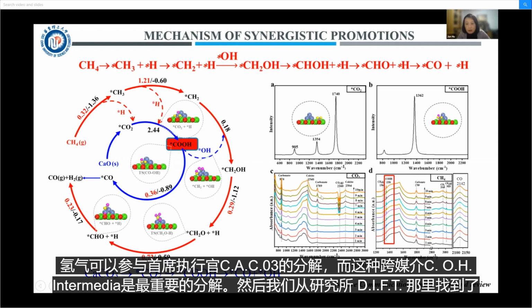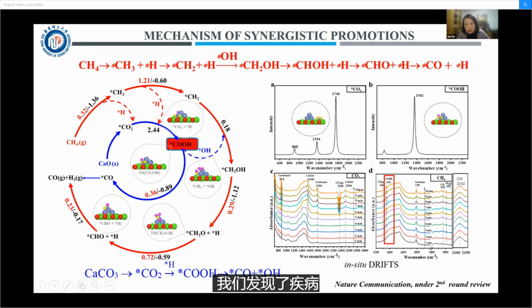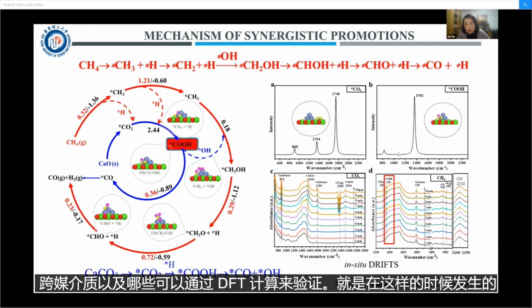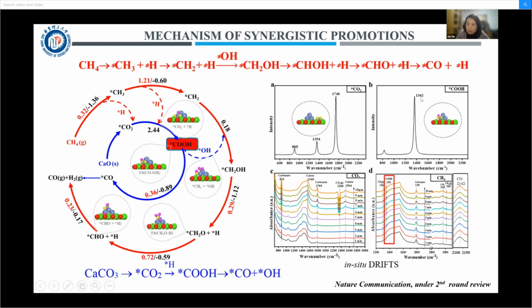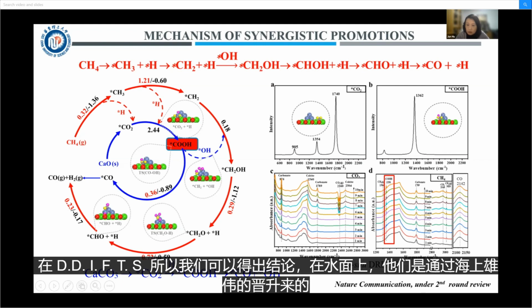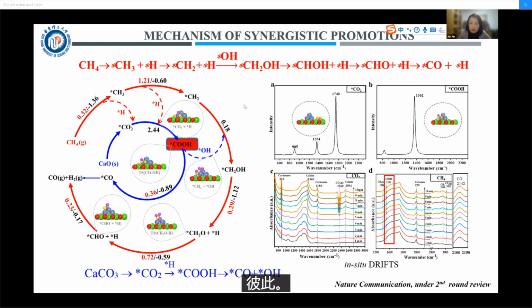And from the in situ DRIFTS, we found these intermediates, which can be verified by the DFT calculation. It occurs at these peaks, and we can find it in the in situ DRIFTS. So we can conclude that at the surface, they show synergistic promotion with each other.